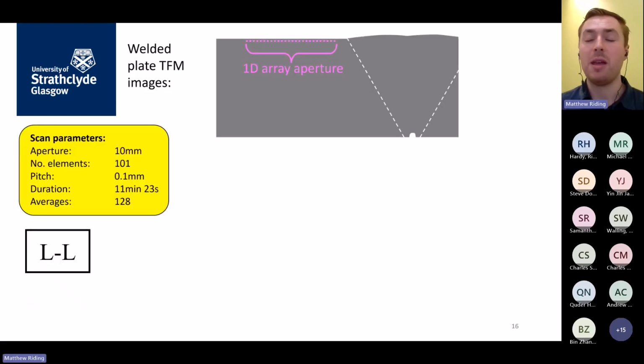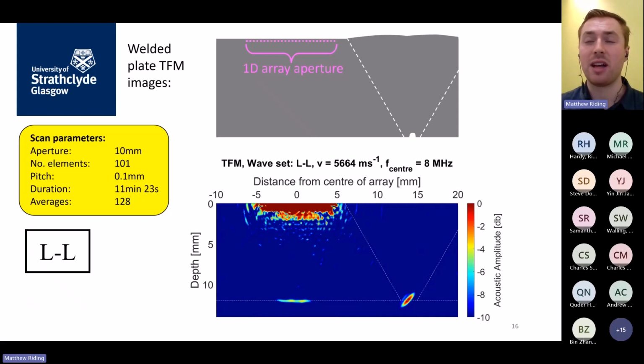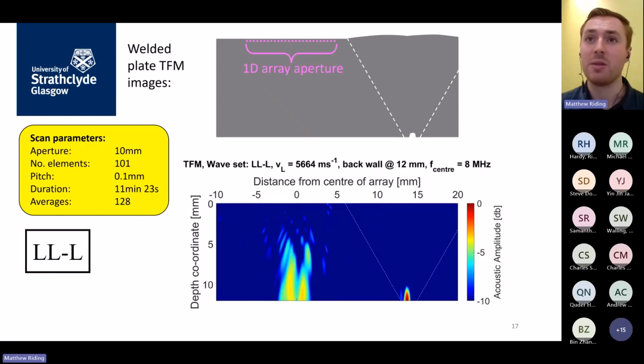So here are some TFM images, and we're able to see the defect very clearly, which is a really exciting result for us. This, at the time, was one of the thickest samples we've examined in terms of the distance of the defect from the surface. So down at 12 millimeters depth, so it's a decently thick plate.